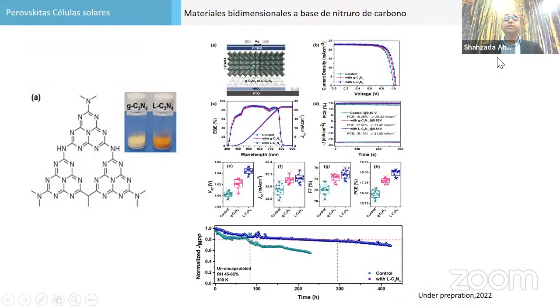Recently, we have been working on these inert 2D materials because they have no functional group. Now we are working on functional 2D materials like carbon nitride. Here we have an amine group, and this amine group will also passivate the perovskite. This carbon nitride is used as an interlayer here.